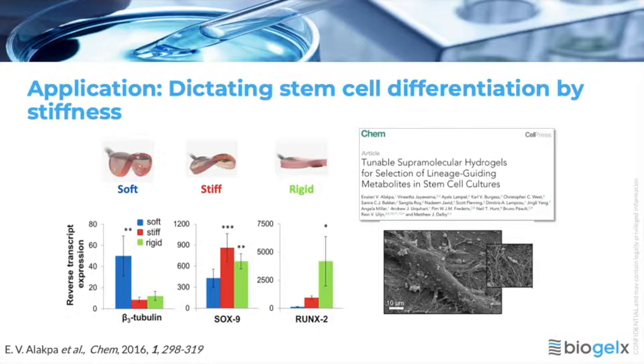And we have a nice application of this tunability here with this publication from a collaborator, Matt Dolby from the University of Glasgow, who has cultured perivascular stem cells using gels of 3 different stiffnesses, and then assessed the expression of markers for neurogenesis, which is the beta-3 tubulin shown in the first graph, chondrogenesis, which is the SOX9 middle graph, and osteogenesis, which is the RUNX2 marker shown here. And with all other conditions remaining equal, it was found that the stiffness of the gel seemed to affect the differentiation of the stem cells. So in the softer gels, the researchers saw more differentiation towards what we would expect for neurogenesis. In the stiff gels, similar to chondrogenesis, and then in the rigid gels, more similar to osteogenesis.